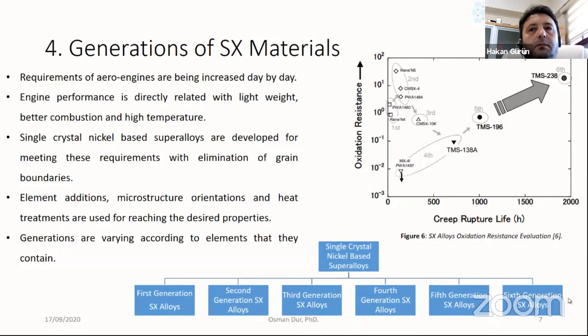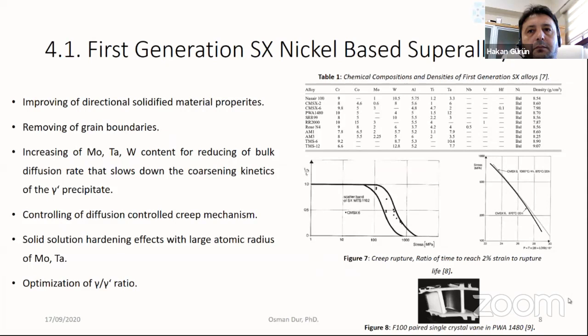As you see in the figure, oxidation resistance of single crystals was increased with different generations. Also, the strength, creep, and other properties were increased. First generation single crystal nickel-based superalloy was derived from directionally solidified materials for increasing creep life. The most important improvement was the removal of grain boundaries. When compared with directionally solidified alloys, molybdenum, tantalum, and tungsten contents are increased for reducing the bulk diffusion rate, which also slows down the coarsening kinetics of the gamma prime precipitate.